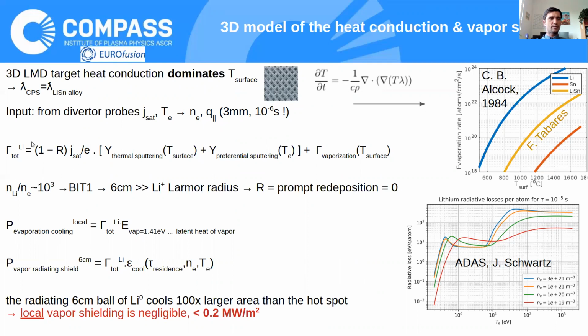So here is how we calculate the total amount of released lithium. We take the deuterium influx, which is the ion saturation current density, and multiply it by 1 minus prompt redeposition, which we believe is really 0, which I will explain on the next viewgraph. The reason is mainly that the mean free path is much larger than the ion Larmor radius, so there is no chance for the ions to return back to the surface.